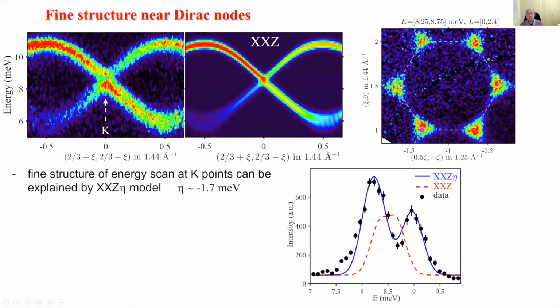And indeed, this is seen experimentally if we look very carefully. So if we do a slice here precisely at the K point, the expectation of the XXZ model is that really they should touch in a very sharp point here. But if we look carefully at the data, there's some broadening here that's beyond the broadening of a single dispersion. And in fact, if we do a scan up here, there's clearly two peaks, whereas if it was the XXZ model, we'd expect a single peak. And the blue line is actually a fit where we vary this anisotropy interaction eta. So the amount of splitting gives us a measure of how strong this anisotropic interaction can be. And some finite interaction actually is compatible with the experimental results.